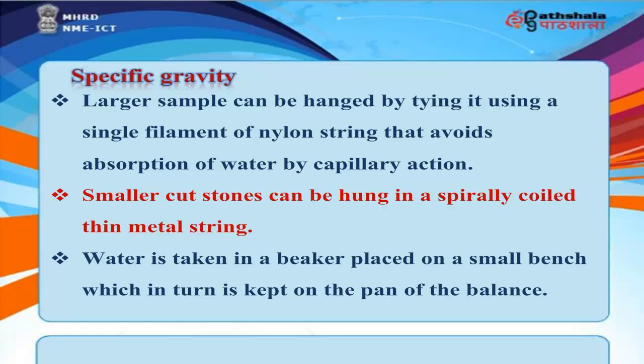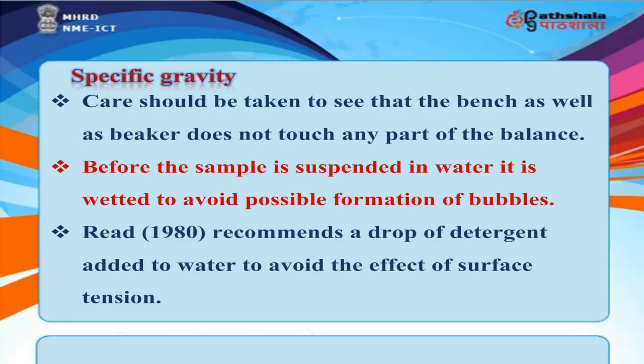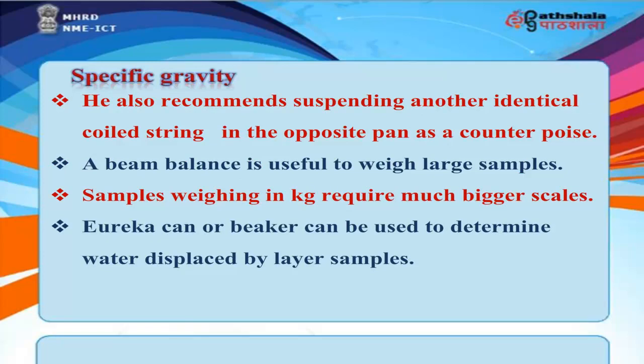Larger samples can be hung by tying them using a single filament of nylon string that avoids absorption of water by capillary action. Smaller cut stones can be hung in a spirally coiled thin metal string. Water is taken in a beaker placed on a small bench, which in turn is kept on the pan of the balance. Care should be taken to see that the bench as well as the beaker does not touch any part of the balance. Before the sample is suspended in water, it is wetted to avoid possible formation of bubbles. Read, 1980, recommends a drop of detergent added to water to avoid the effect of surface tension. He also recommends suspending another identical coiled string in the opposite pan as a counterpoise.